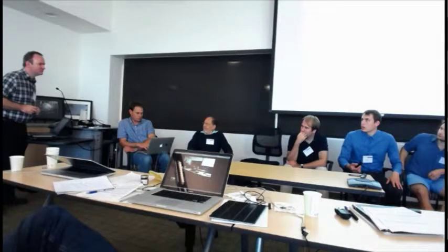If you're doing a weighted average, and you're merely dividing by 0... I said, apply a weight of 0 if the calculated partiality is less than 0.25. Could be, yeah. Sounds about right. Now, your suggestion is similar, just a more accurate weighting, not 1 and 0. There's something I found in Numerical Recipes called a Wiener filter. Yeah, that's good. If you think you know what the signal looks like, then you multiply the data by that function, and that's the optimum weight. So then you're multiplying by the partiality and not dividing. For weighting, yeah. But it's a nice way to think about it.